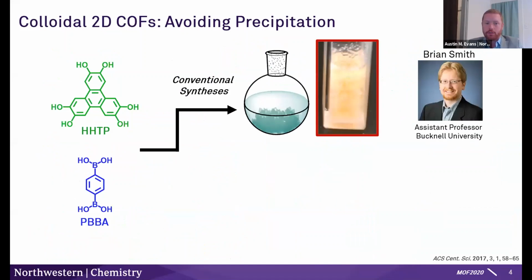Okay, so a few years ago, all COFs essentially were synthesized as polycrystalline powders. There are a few examples that would buck that trend. There are some polycrystalline films, but largely the polycrystalline powders were the primary morphology that was obtained in all syntheses. And that is fundamentally limiting, because if we can only synthesize polycrystalline powders, one, they're challenging to investigate from a property standpoint, they're challenging to fabricate in devices, and also the domain sizes that we were obtaining in polycrystalline powders were quite small and defect prone. So beyond the fact that they're challenging to study and integrate into device architectures, they're also not quite representative of the bulk material we intended to synthesize.